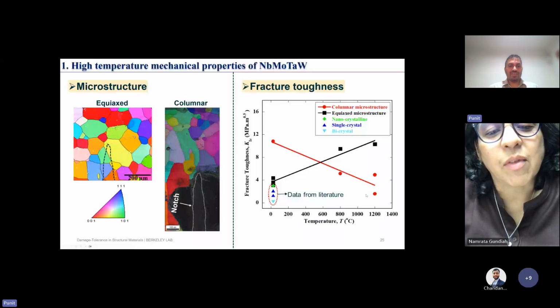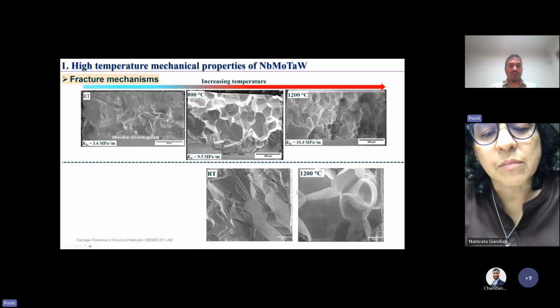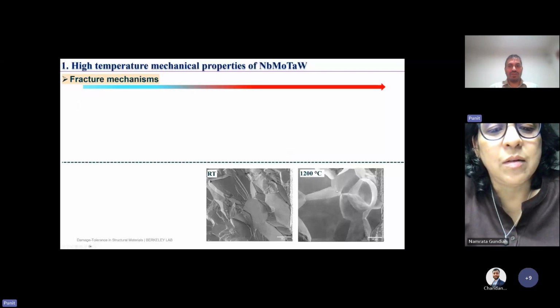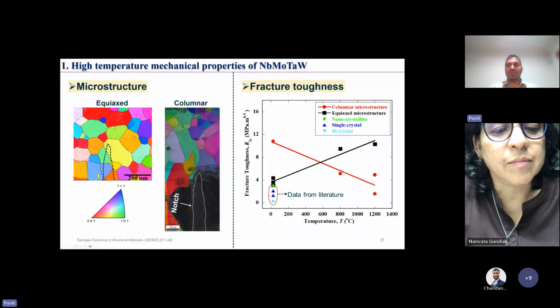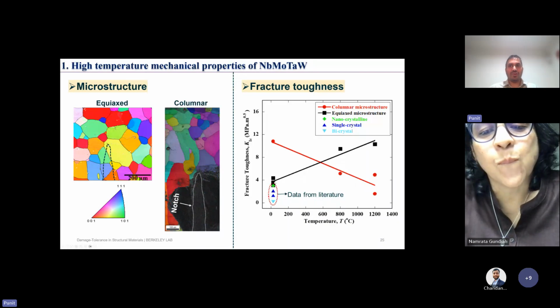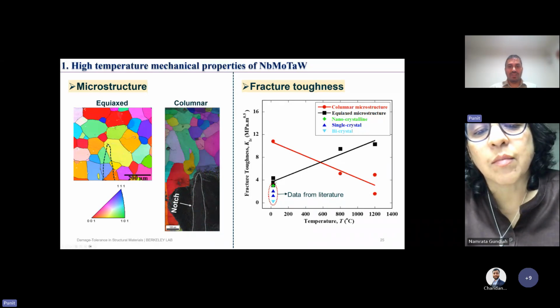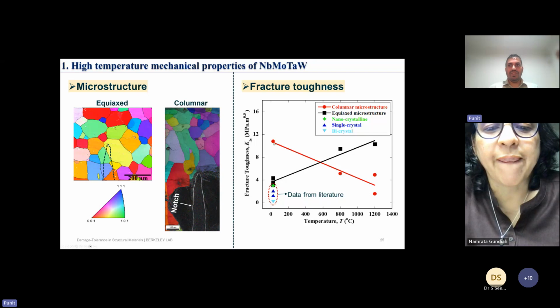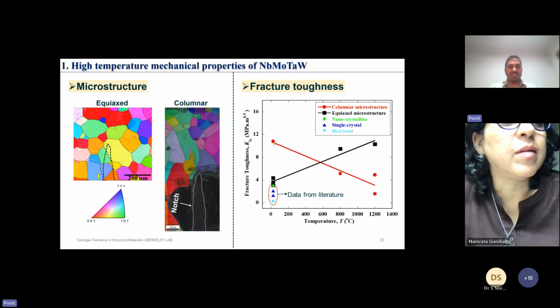Yeah. So I think that's a really nice question. If you look at the fracture data, I think you are right about not having enough data to actually comment on how different it is. But basically why we were doing that is because at room temperature we got data values similar to what we get in nanocrystalline materials for the fracture toughness. We did multiple tests here, 3 tests for the equiaxed microstructure and the columnar microstructure. The challenge with these tests was that we did not know how the microstructure ahead of the crack tip looks before we actually fractured the sample and looked later on. So we were not able to choose which sample is for which condition.